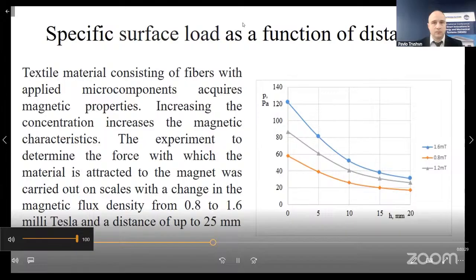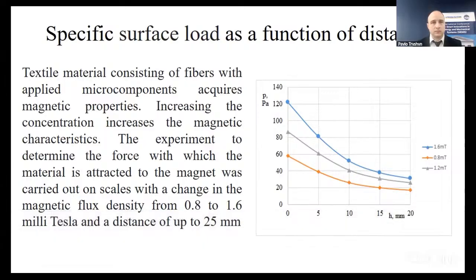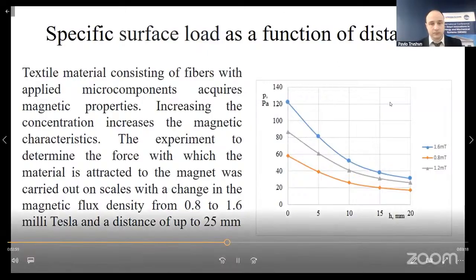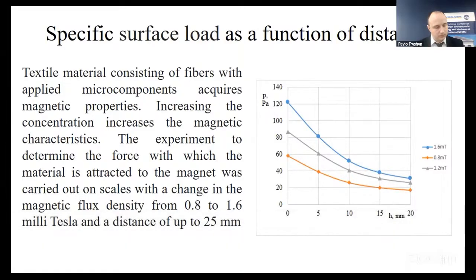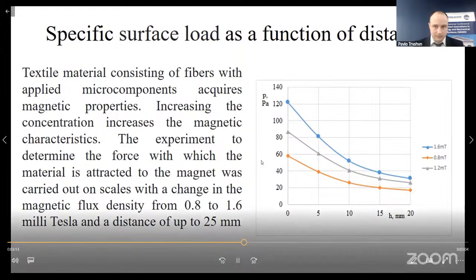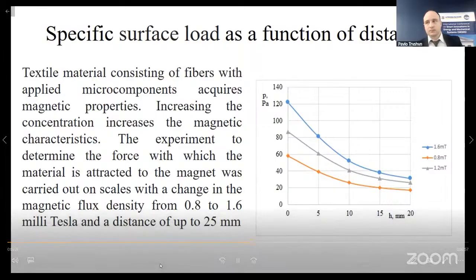Increasing the concentration increases the magnetic characteristics. The experiment to determine the force with which the material is attracted to the magnet was carried out on scales with a change in the magnetic flux density from 0.8 to 1.6 millitesla and a distance of up to 25 millimeters.